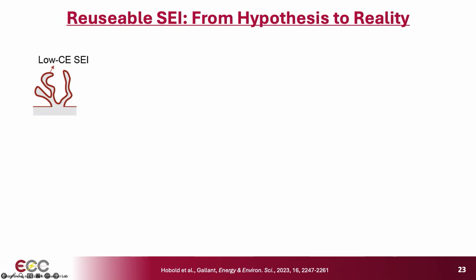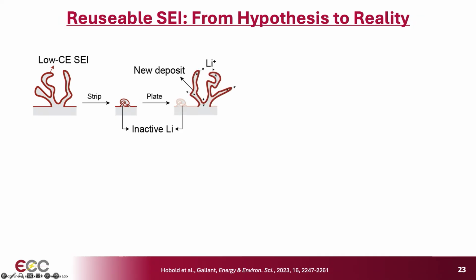So we were really interested in understanding why high Coulombic efficiency electrolytes have increasing J naught. This turned out to be very hard to measure, but we pulled it together with the following model that we proposed. For low Coulombic efficiency systems, you plate lithium, you form an SEI as depicted in the red outline shown here. And then when you strip it, you're left with some inactive material on the surface. Now, if this is low Coulombic efficiency and it has low exchange, then there's no preference necessarily to reuse this material to plate lithium.